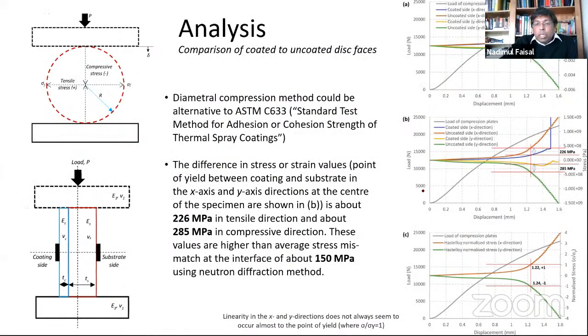So here are some results. You can see that this is a load profile, and then these are the strains. Anything below 0 is compressive. Anything above this is tensile mode. So you can see the point where it is changing to nonlinear. This is the point where we compared the substrate and the coating. So you can compare the strain data coming from the substrate, and the strain data coming from the coating and substrate, and see what those values are and take the difference of it.